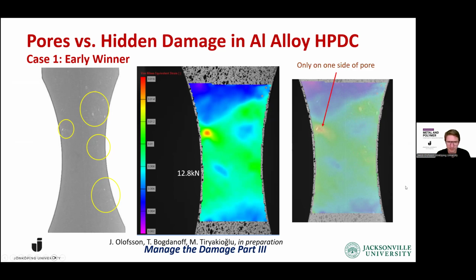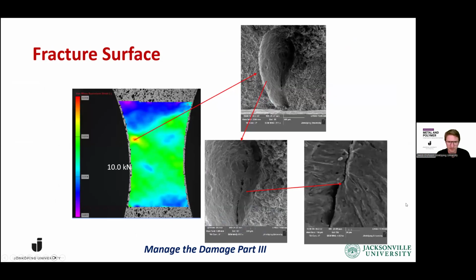So proceeding and pulling this to the fracture in the next slide. Here we can see what we can then see in the microstructure on the fracture surface. You see the pore, the visible porosity that has been visible to X-ray, but zooming into this, we can also see that there is more cracking, and in these cracks you will see that there is oxide in the bottom of this pore that has also caused this crack to propagate, and also what causes the strain concentration to go to the right instead of to the left, to the surface, as we would expect here.